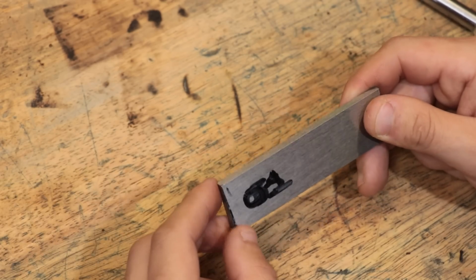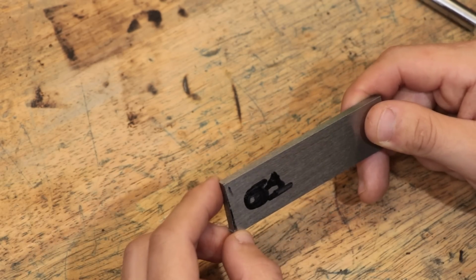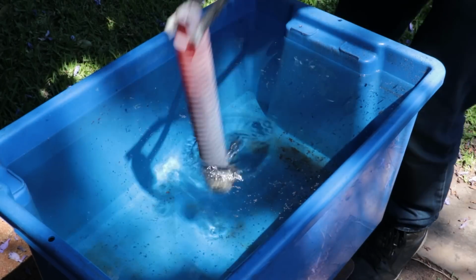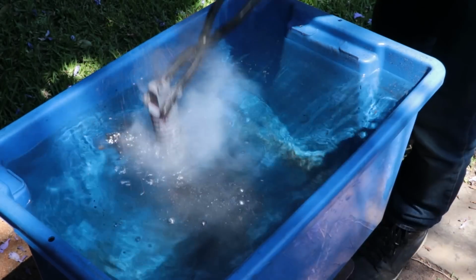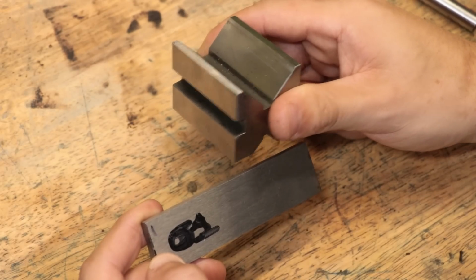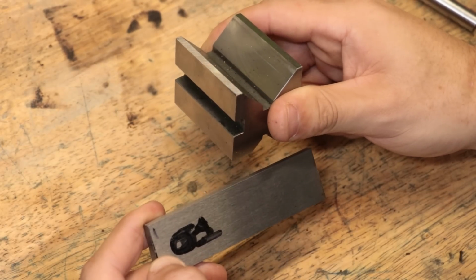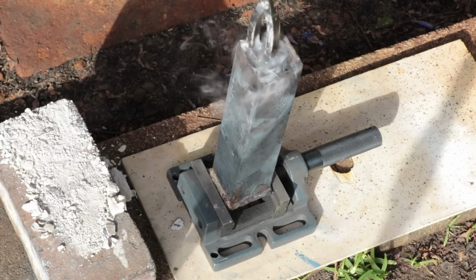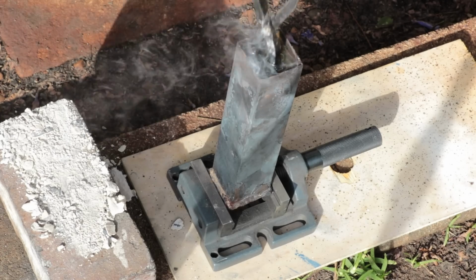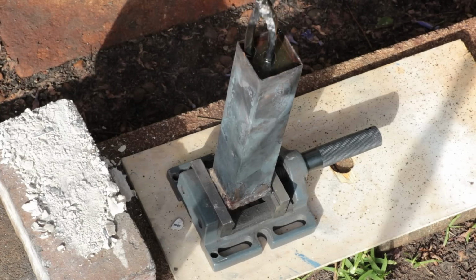With W1 or regular carbon steel, we need to get it cooled from red hot to about 200 degrees in the span of a second. With our O1 steel, it's closer to about 9 seconds. So effectively, we're able to cool it slower, risk less distortion, yet still achieve our high hardness.